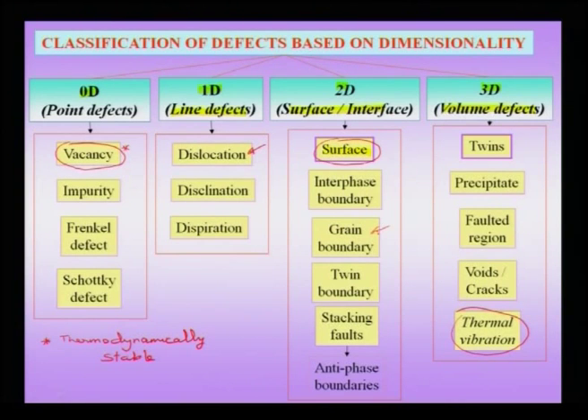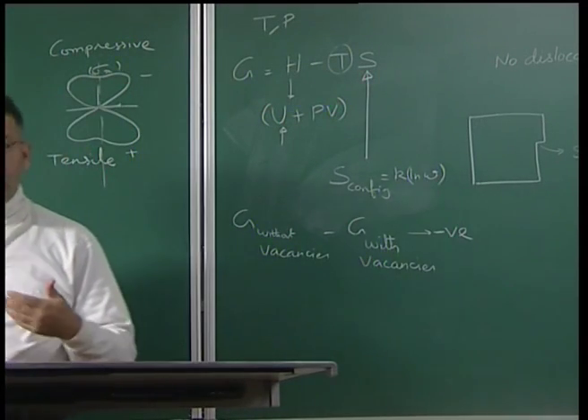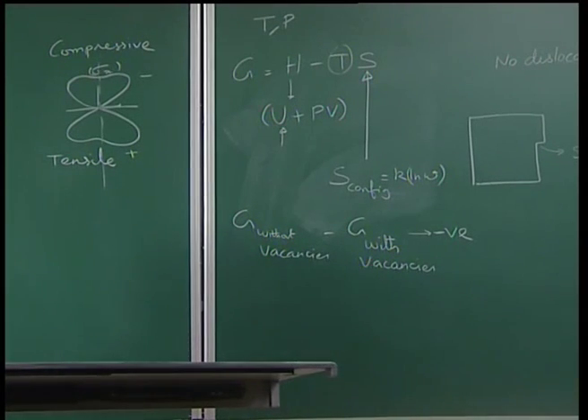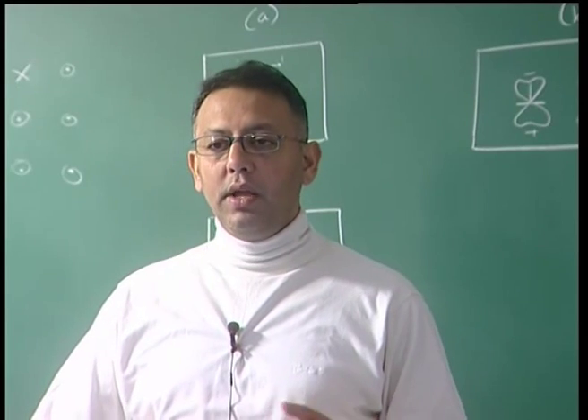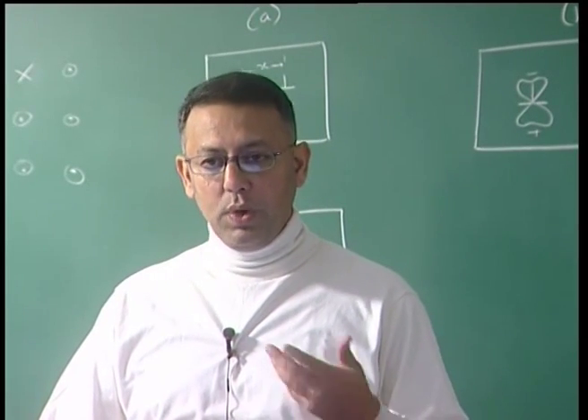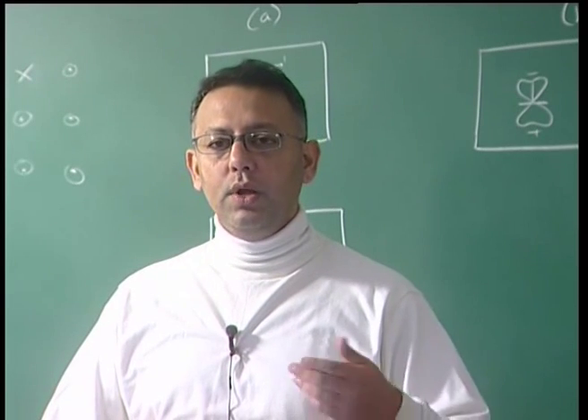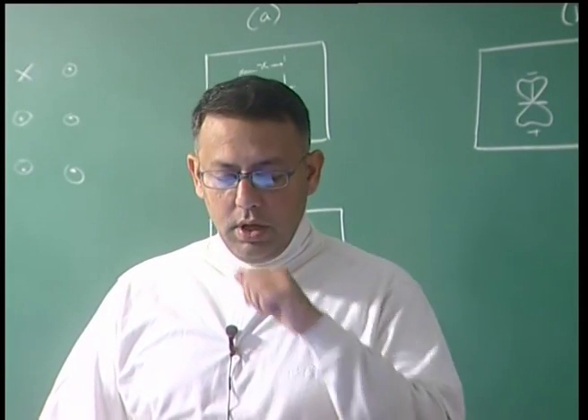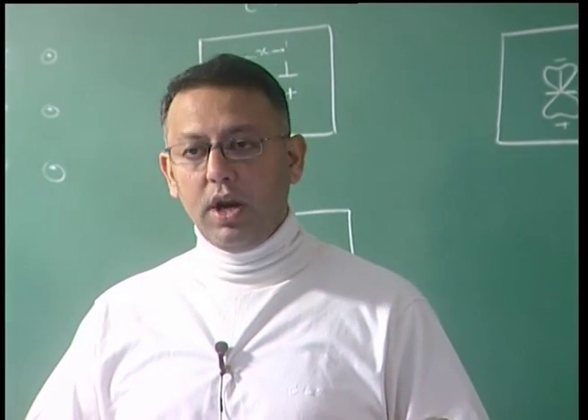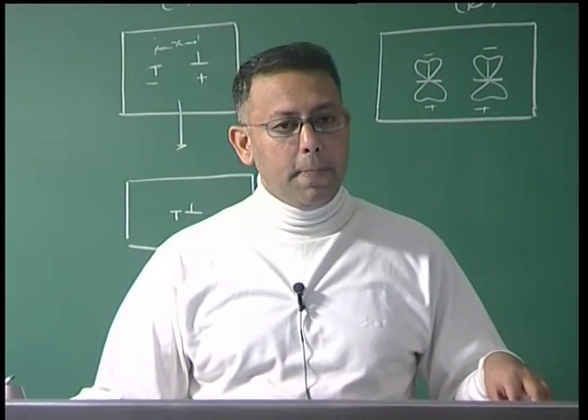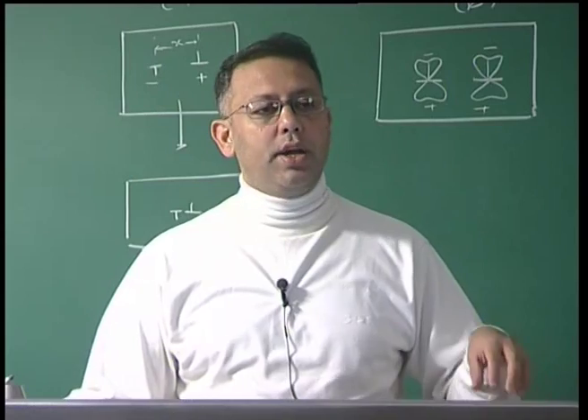If I heat to a higher temperature, more vacancies become stable because temperature is the weighting term for entropy. When I slowly cool down, the number of vacancies — if given opportunity — decreases to reach a new equilibrium at lower temperature. On the other hand, if a system has dislocations or grain boundaries and I heat it, there will be a tendency for dislocations and grain boundaries to leave the crystal, reducing the Gibbs free energy. Surface and thermal vibration are unavoidable; vacancies, though defects, are thermodynamically stable.